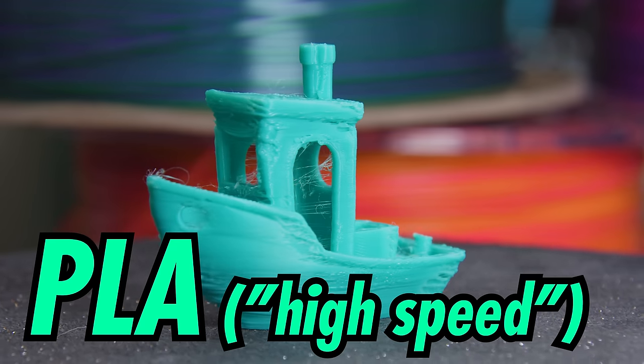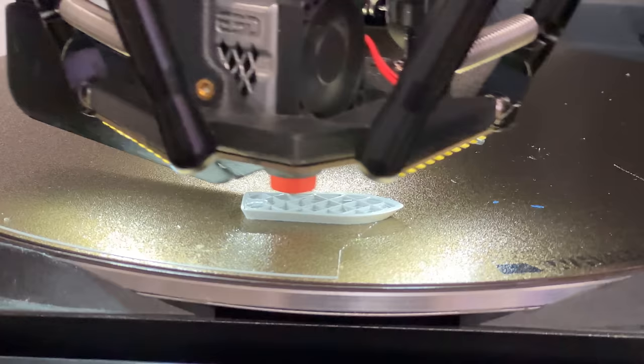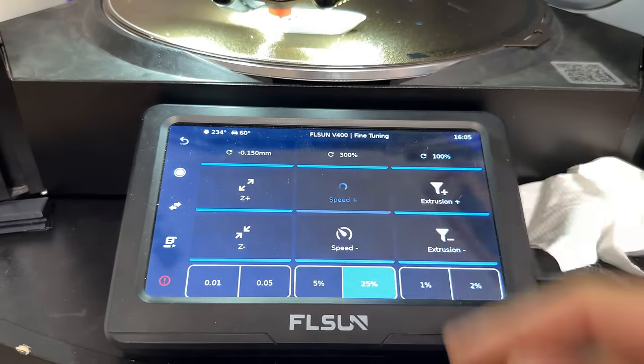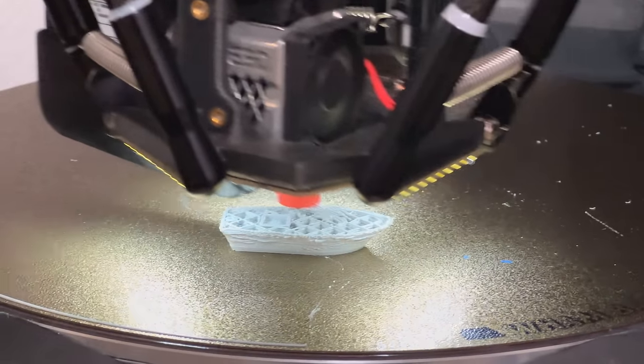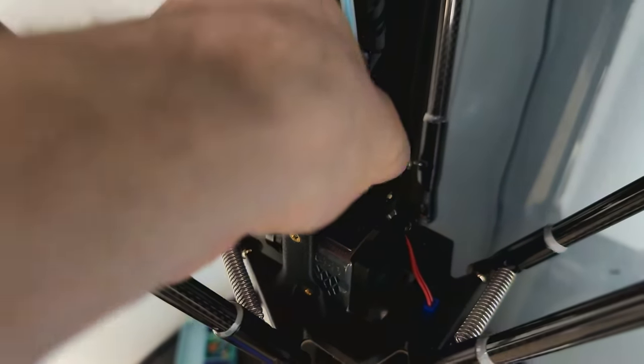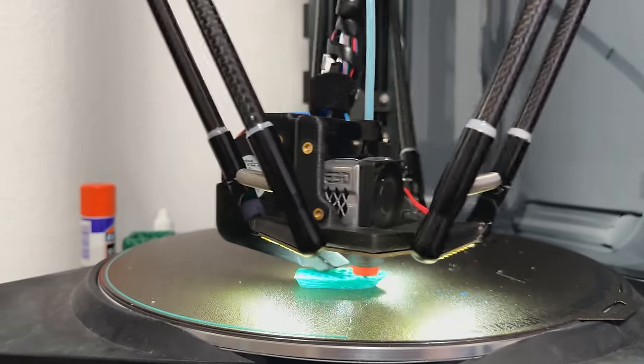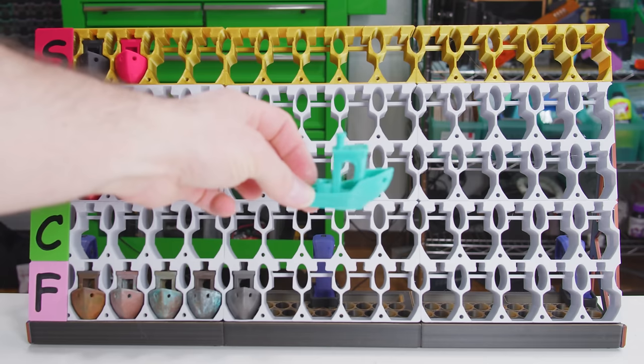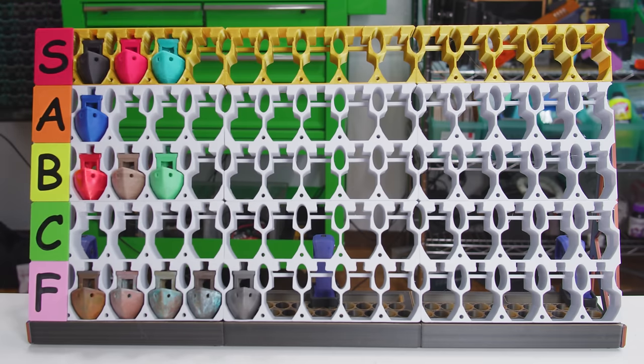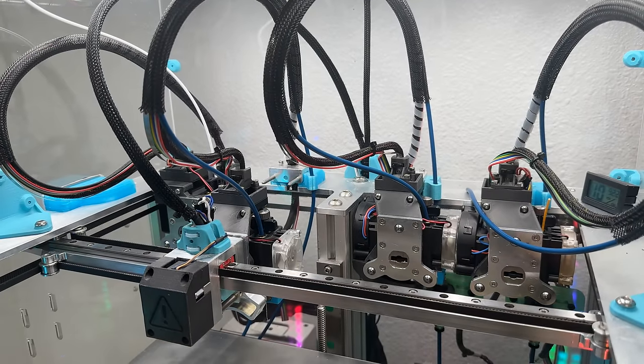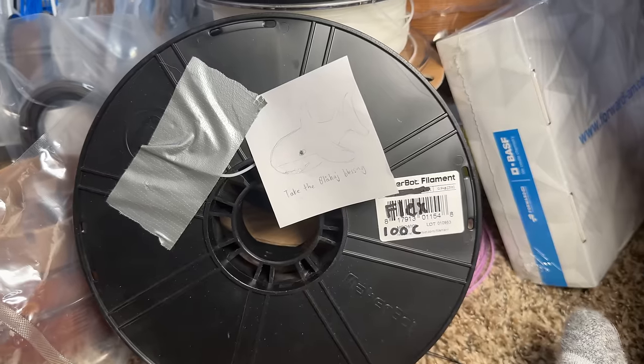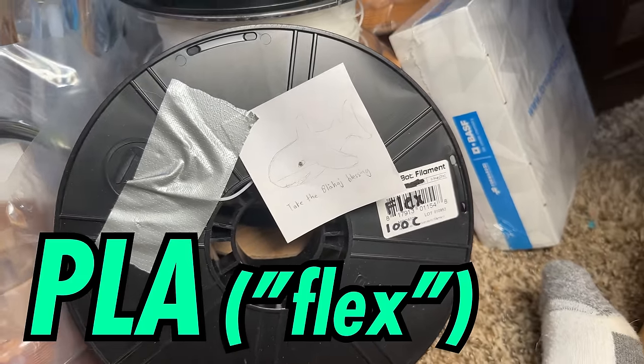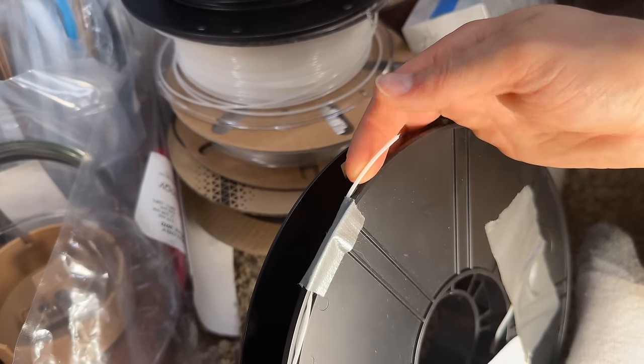The third is high-speed PLA, a dubious name for what's a genuinely useful filament. You can run regular PLA pretty quick, but above 300 millimeters a second, you just can't force enough pure PLA through the hot end to keep up with the motion system. High-speed PLA melts at a lower temperature and has a reduced viscosity, so you can crank that hog to table-wobbling turbo speed. Considering how little heat it takes to soften normal PLA, this can be a real problem in hot climates. Still, I'm gonna put high-speed PLA in S tier. S for speed. There is just nothing more important than finishing projects faster. A few hours can make all the difference. Of course, you only get those hours if regular PLA is holding your printer back from rolling around at the speed of sound. S tier segue.